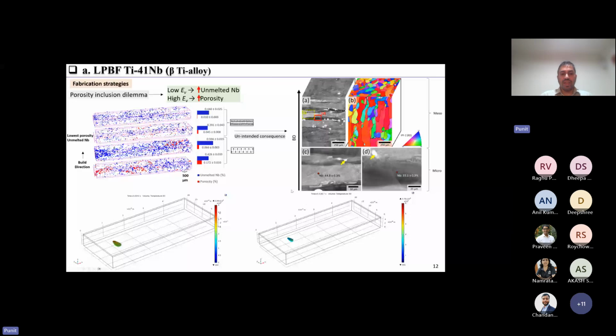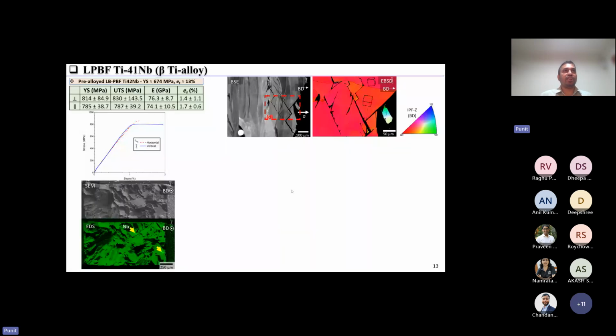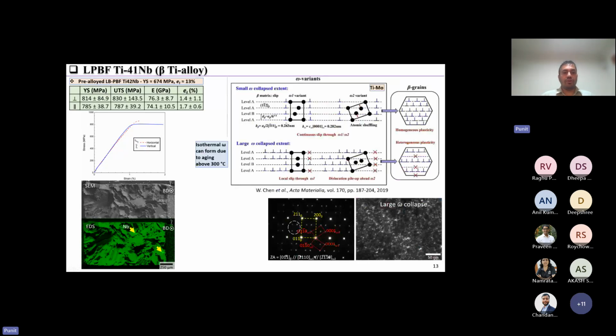And then we went ahead and did some mechanical testing, starting with tensile testing of this material. One of the things we observed was that this material was showing really low plasticity. It was showing higher strength compared to a similar composition beta titanium alloy, but it was showing no ductility at all. When we looked at the fracture surface, we saw cleavage fracture, along the specific cleavage planes where BCC materials usually fracture. So we were trying to understand why we have such poor ductility in this material.